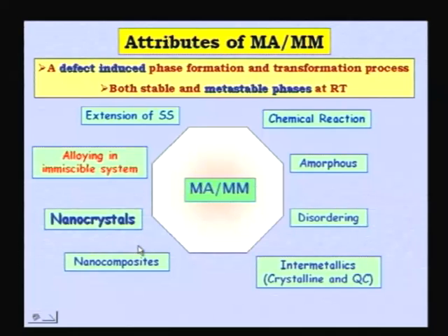So what can happen? As I told you, it can give you nanocrystals, it can give you nanocomposites if you are putting in more than one type of material. So you can have nanocomposites. For example, if you take a nickel based alloy, nickel and yttria, you can break it down to very fine size, and ultimately if the energies are high enough, you can make a nanocomposite of nickel into which you can have yttria.